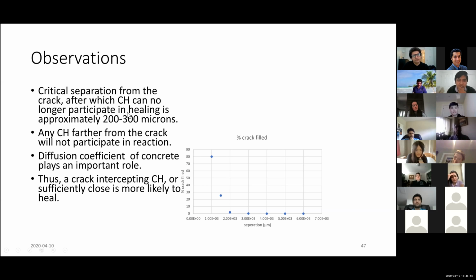One observation that I could make for now using this 1D model, assuming the concrete porosity or concrete diffusivity that has been reported in most of the literature, is this. We can see the separation between the crack and calcium hydroxide, and this is the percentage of crack filled, so how much reaction is happening inside the crack. If the separation between calcium hydroxide and the crack inside the concrete is more than 300 micrometers, there is roughly no contribution of that calcium hydroxide to healing. And if it's close, it contributes to the healing.